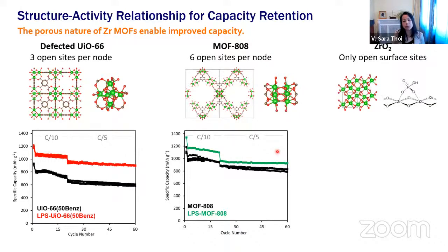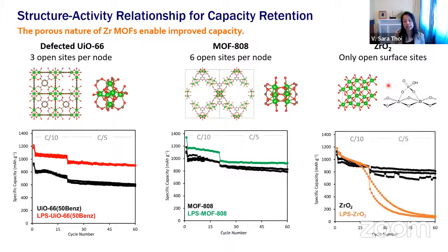Finally, we need to test whether it is just the zirconium cluster that's doing all the work. And so what we tested are a non-porous zirconia, which only has open surface sites for thiophosphate to bind. And that's very similar to how we know phosphate binding to the zirconium centers. And when we did this, we see that our strategy of using LPS simply doesn't work. You see a very large capacity fade. And that indicates to us that the molecular nature of our metal-organic framework, its porosity and structural integrity, is essential in order for the thiophosphate to cycle our polysulfides within the system.